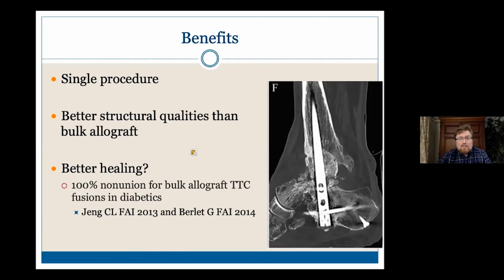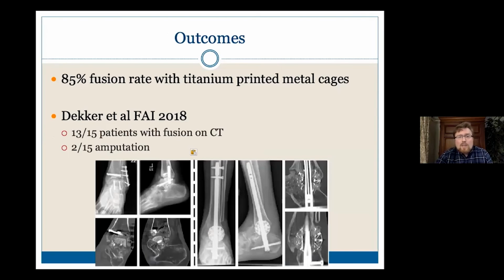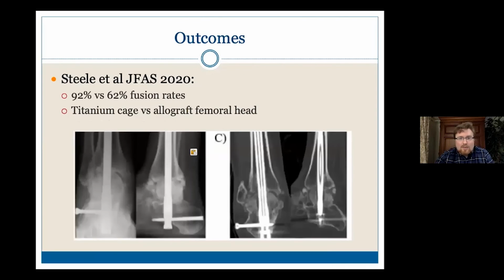And so from the benefits, we do know, especially in diabetics, that bulk allograft TTCs rarely, if ever, fuse. And so 2 studies in 2013-14 showed really 100% of them had non-unions around bulk allograft if there was a diabetic. And with the fusion rates around titanium printed cages, we're getting 85+%. And so 2 studies here with 15 patients, 13 of them went on to have a good outcome, pain-free walking and fusion, and the other 2 ended up, unfortunately, with amputations. But certainly if we're thinking about doing any of these, we're in the limb salvage world for sure. And this was another study from the same group looking at fusions with allograft versus the metal cages, showing 92 versus 62% overall fusion rates.